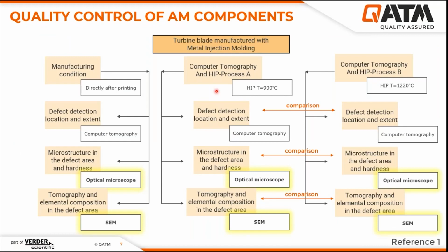Here is an example of the quality control of an additive manufacturing component. The case here is a turbine blade. On the left-hand side, we have the manufacturing condition, which in traditional casting we call the cast condition. Here is the computer tomography and the hot isostatic press process. The hot isostatic press is at a temperature of 900 degrees, and on the right-hand side, we have a temperature of 1220. And then we want to see which one is better.